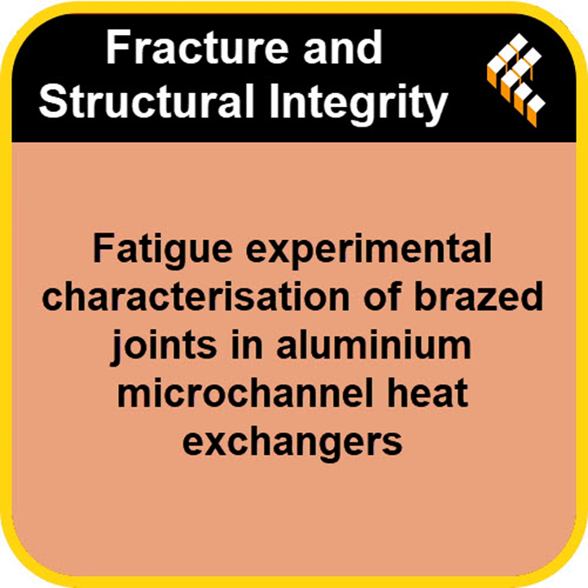Exactly. But the fact that this endurance limit is so much lower than the strength of the base materials themselves confirms the critical point. The joint, with its inherent geometric stress riser at the toe and its mixed metallurgy, is absolutely the dominant factor controlling fatigue life. The base material can be super strong on its own. Doesn't matter as much. But the joint itself sets the ultimate limit for the whole component's lifespan under cyclic load. That's the takeaway. It's the fatigue critical region.